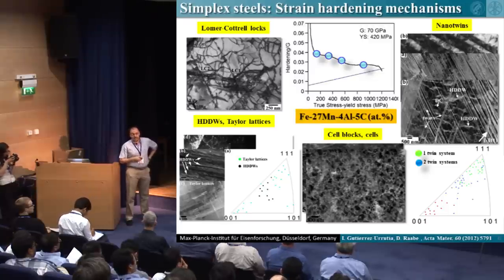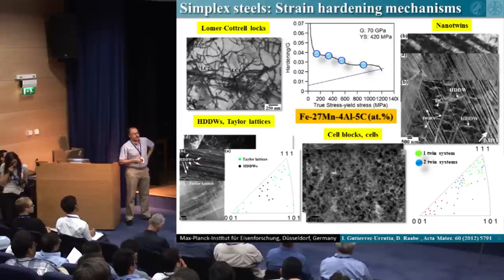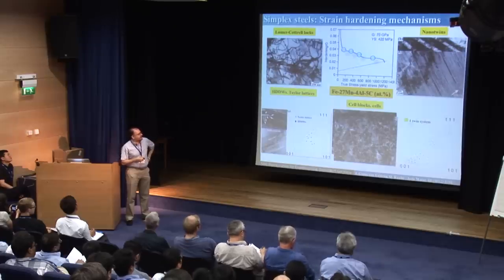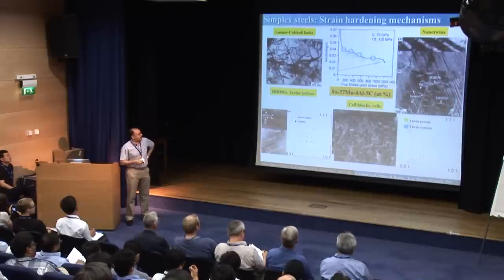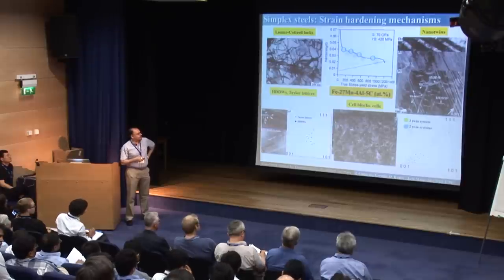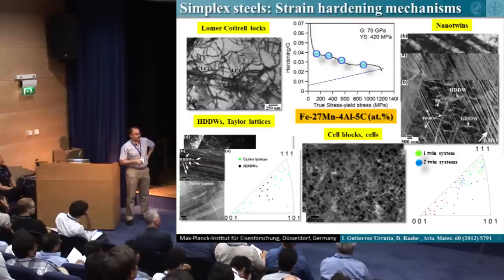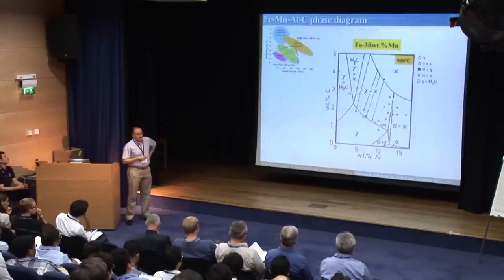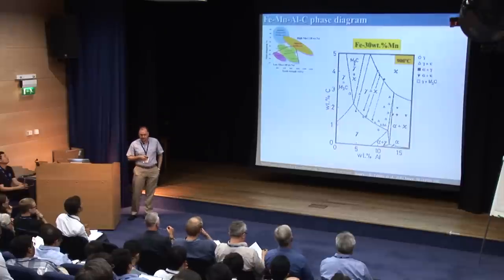Again, this is a stress-based mechanism, so even at higher stress levels, we have a twin structure that is characterized by a corresponding crystallographic orientation dependence, which means that under uniaxial tensile stress, we have grains close to 1 1 2 with a lamellar twin structure. Only one twin system is mainly active. In grains close to 1 1 1 parallel to the tensile axis, we have multiple twinning systems. Of course, we even have grains that are stable against twinning. This is basically due to the nature of slip and twinning, which is stress-based. So we need to understand the crystallographic orientation dependence of all these features. So this corresponds to simplex steels.